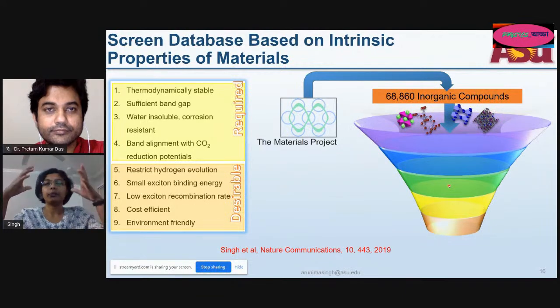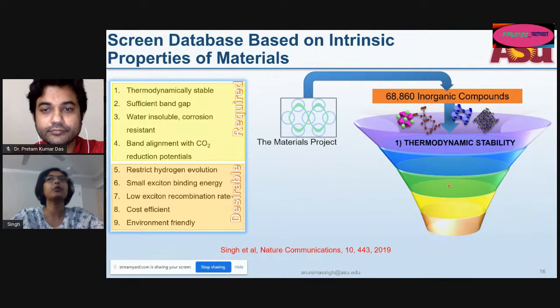And we thought, let's look at these 70,000 compounds and see if we can identify materials which will match the conditions for good photocatalysts. What we did was a successive screening for the properties to minimize the number of computations which we had to do. And the first property we looked at was the thermodynamic stability. The Materials Project database has the energy above hull, which is the energy with respect to the most stable solids at that composition for the materials.